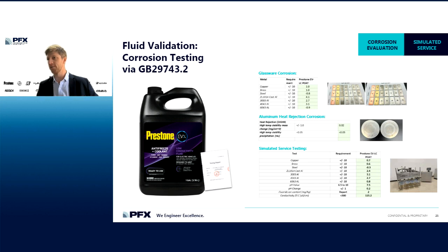We finish this out with some additional corrosion testing. We have a high temperature aluminum heat rejection test. If you're familiar with ASTM test methods, this is a modified version of the D4340, with the modifications being to the type of aluminum used. And then we move on to the simulated service test. So you'll see the results for our corrosion are very acceptable per the GB specification. And then we run the simulated service test.